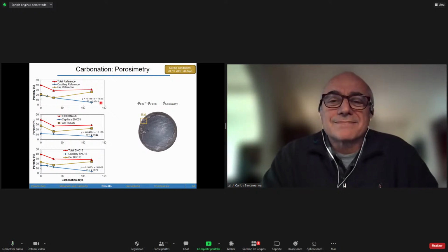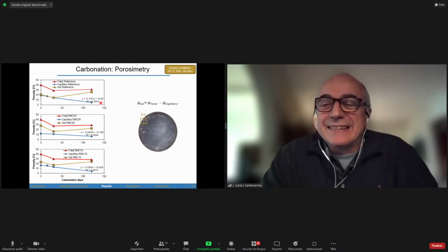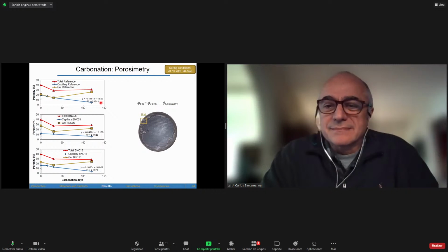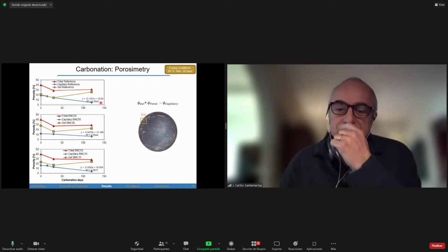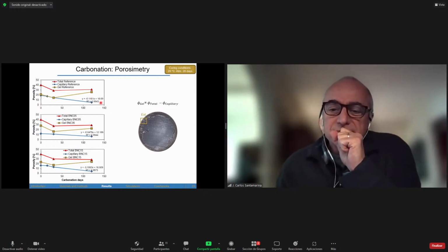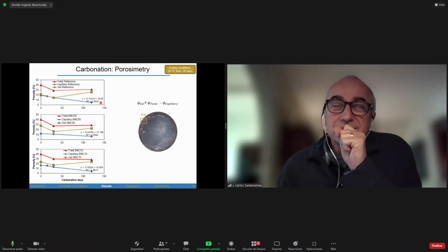And for me, I'm pushing you to tell me, is there a dramatic change in the physics? I think it depends. For instance, in this case, gel porosity is considered to be the CSH porosity. So initially, to simplify the facts, we use this, but in order to have the real gel porosity of CSH, we should, for each sample, calculate the CSH porosity separately. And then we can say, okay, this is total, this is gel, and this is capillary porosity.